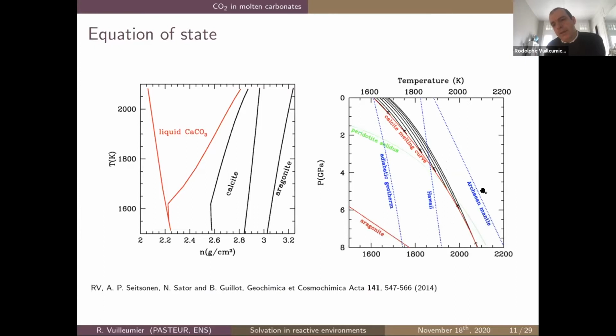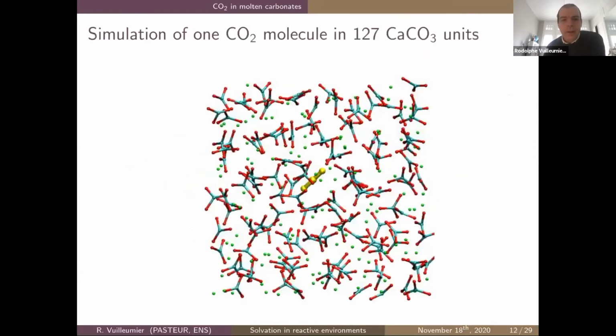And we see that in the Archean mantle, which was much hotter, the molten carbonate could indeed reach the surface, and there are many traces of that, especially Yellowstone Park, which is a manifestation of carbonates that have reached the surface on a large scale. But what we would like to address is CO2 in this system. So this system is like CaO with stoichiometric CO2. We can still put more CO2 in it.